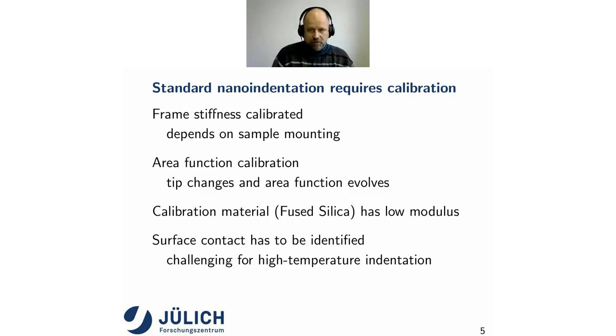If you want to do that, then generally you have to determine the frame stiffness beforehand. Basically, how is your sample mounted? How is your sample glued? How is the tip mounted? You have to know the shape of your tip. That is called the area function calibration, and how this area evolves over time. To do that, you generally use a calibration material. Fused silica is the material of choice, which has a rather low Young's modulus. So if you want to do indentations in, I don't know, steel or tungsten, you do some extrapolation, which is also prone to some inaccuracy.